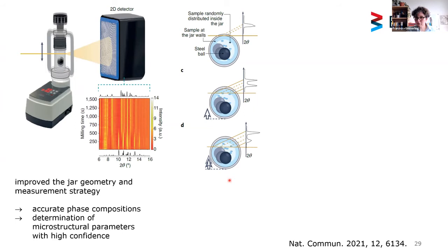Just briefly, if you perform a normal X-ray diffraction experiment, your sample is at a fixed point, but now you have seen how this jar wobbles around. So we usually get overlays of different positions where information gets scattered. And if we choose the position where we measure very wisely, we end up with high quality data that can really now be used for Rietveld refinement. And we also get more information on microstructural parameters.